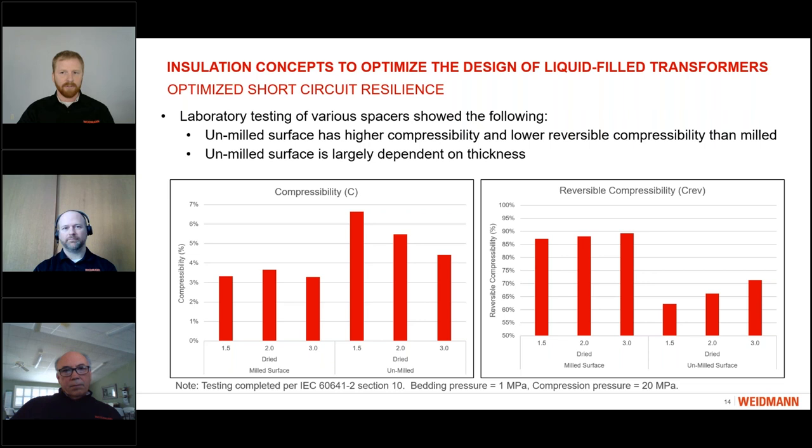Whereas on the milled surface materials, first we see higher reversible compressibility, meaning more of that thickness that was compressed out actually returned, and it is much more consistent between different thicknesses of spacers.